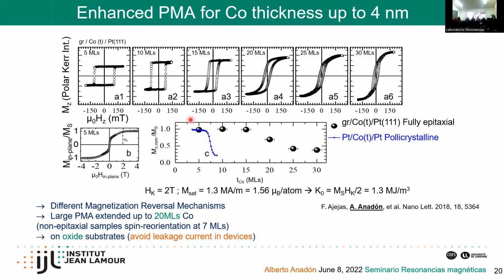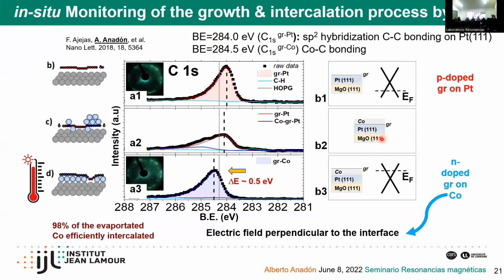But if you have a graphene cobalt platinum system, this perpendicular magnetic anisotropy is held up to almost 4 nanometers. So you can have much thicker cobalt while still having perpendicular magnetic anisotropy. So in this system, we were very interested in understanding what was going on in the graphene-related interfaces, basically in our cobalt graphene interface. So we studied how the intercalation process of cobalt went.